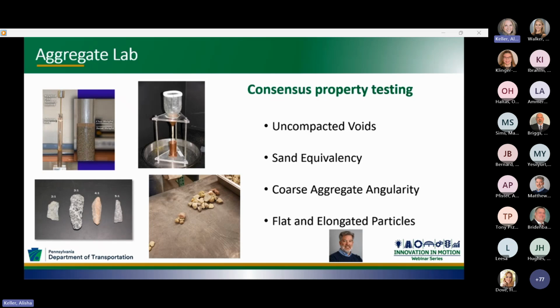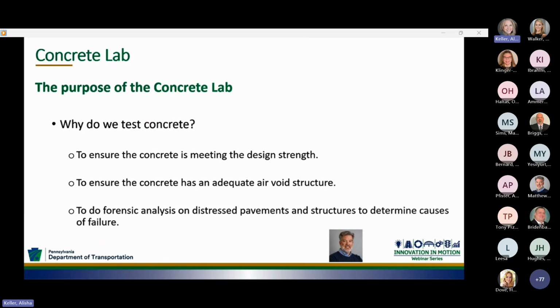Flat and elongated particles determines the percentage of coarse aggregate particles that have a ratio of length to thickness greater than a specified value. This test ensures pavement durability by limiting weak, brittle particles that break during compaction. The second lab area I would like to talk about is the concrete lab. The concrete lab is managed by Seth Wolfinger. The main function of the concrete lab is to perform testing on cured concrete to ensure it's meeting its design strength and ensuring it has an adequate air void structure.